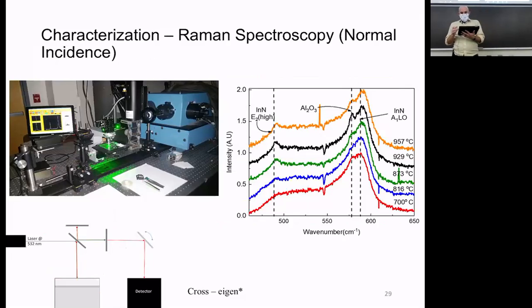We look at Raman spectroscopy. Raman spectroscopy is just the low energy absorptions that are, again, due to the crystal structure. I expose the crystal to high energy light. I catch the reflected light, and instead of looking at the pure elastic reflection, I look at the inelastic reflections. And I can judge how much energy shift the inelastic reflection has had, and that correlates to these shifts right here. So this is not truly a wave number plot, but a wave number shift plot. And you can see right here, and right here, I had light that was absorbed and re-emitted at a slightly different energy than I started off with. And they correlate again to the structure of the material. This one here particularly correlates to how good the crystal structure is. How uniform is it?